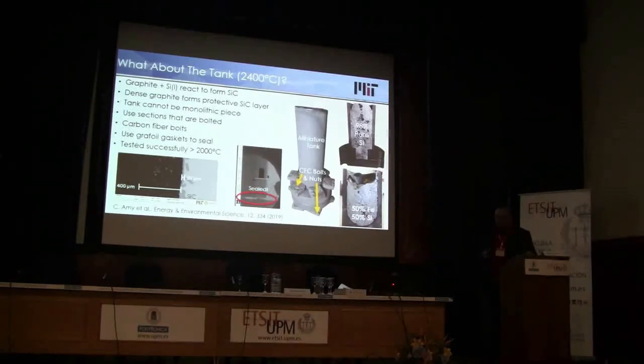But if you use sufficiently dense graphite, that reaction proceeds to a point where you then fill the pores, and then it stops. And then you end up kinetically limited by further diffusion of carbon through silicon to get out and make more silicon carbide. And it turns out, we're lucky, that diffusion is extremely slow, such that basically it starts reacting and then it finishes, and then it can sit there for 100 years or so without making roughly another 10 to 100 micron more of silicon carbide. So that reaction is kinetically limited, or let me say it's diffusion limited.